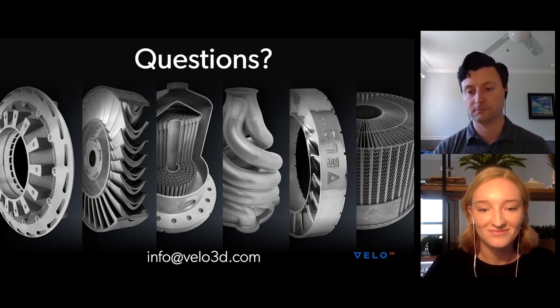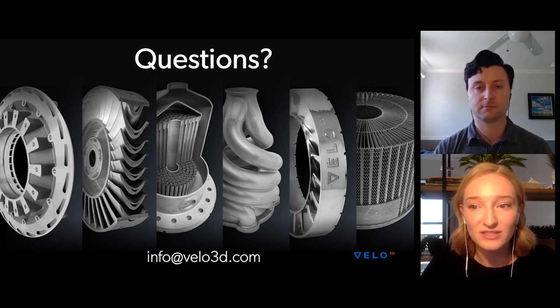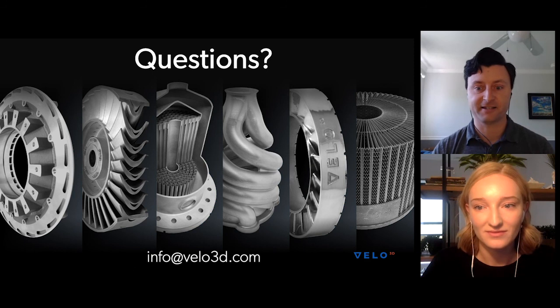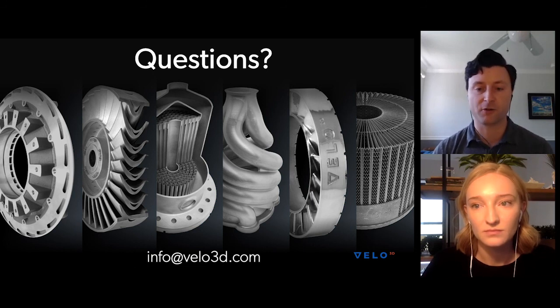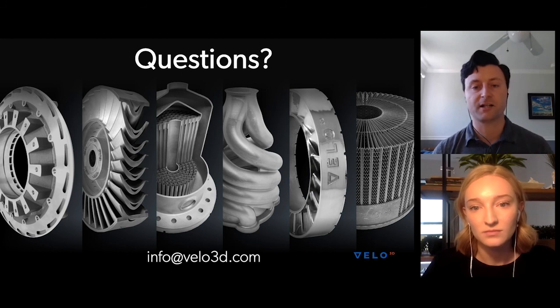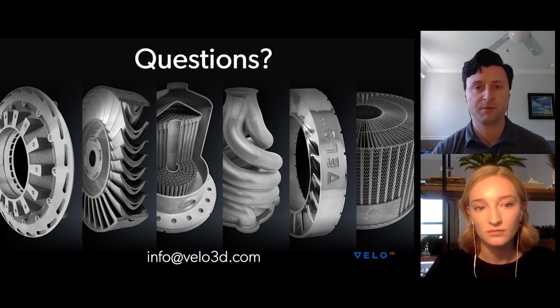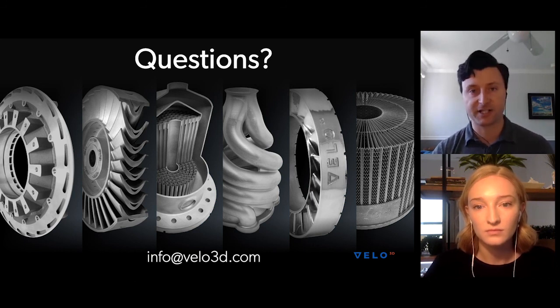Awesome. Another one. Ti-64 can be adversely affected by oxygen environments. What is the environment for Sapphire? Yeah, that's absolutely true. And I think it depends on the grade of the titanium, the Ti-64 you're working with also. So like in medical orthopedics, when you're working with grade 23, with a very low oxygen content, it's important to be printing in a very controlled oxygen environment. So our system's designed to be able to run below 10 ppm oxygen in the build chamber. Often when we're running titanium, we're running it in an actively controlled oxygen. So we'll run at something like 150 to 200 ppm, depending on what the desired outcome is. But actively control that so that you know for a fact what the oxygen is and can keep it at a very, very low oxygen level throughout the entire build.